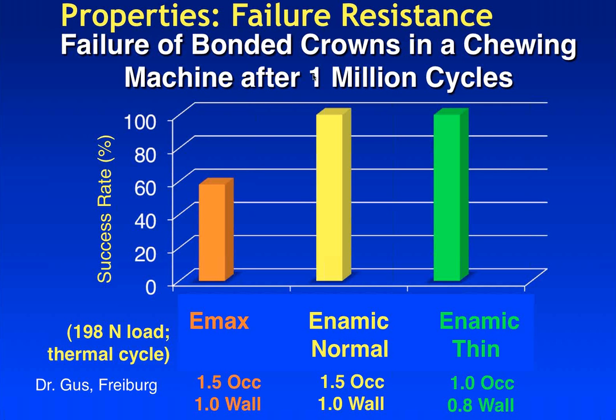And the endpoint was to see how many survived this onslaught of thermal cycling and chewing stress in water during the test. For Emax, only about 50% survived. For Enamic, survival was 100%, and this was comparing 1.5 millimeters occlusal thickness and 1 millimeter wall thickness. Now, when they went to a thinner occlusal thickness and wall thickness down to 1 millimeter, you've also got 100% survival. I don't know exactly how thin you can go, and VITA doesn't recommend you go that thin, but you can look at the data and make your own decision.